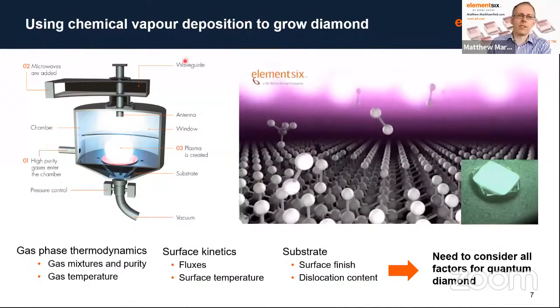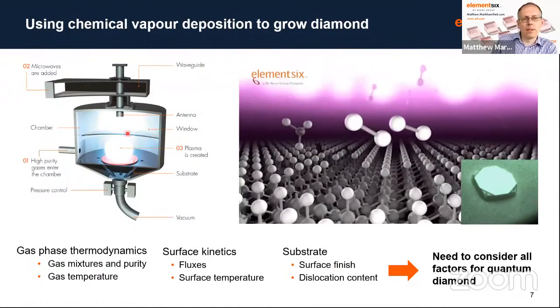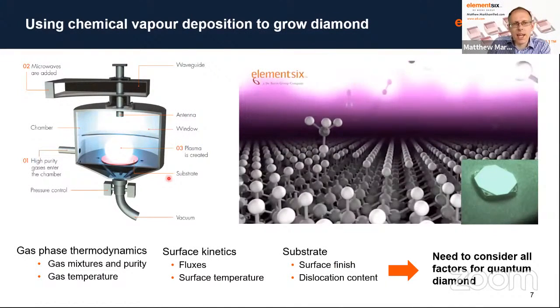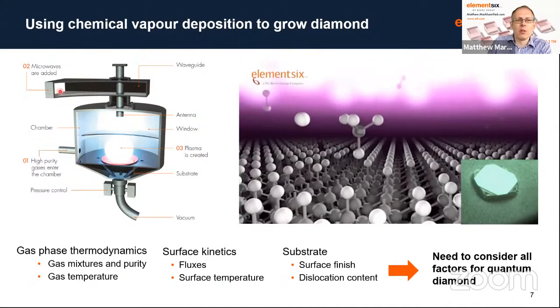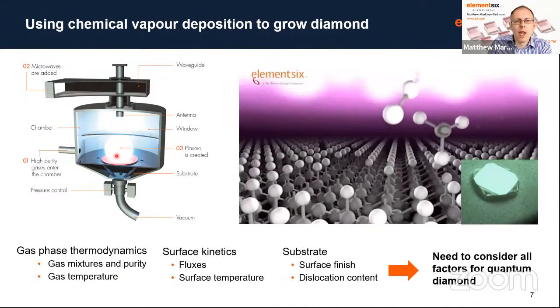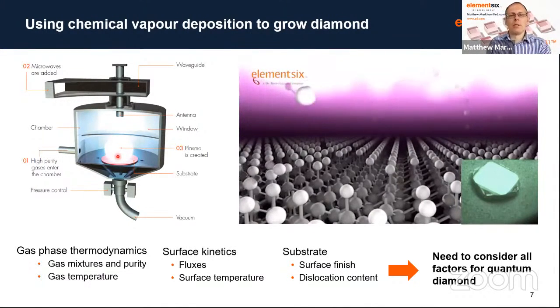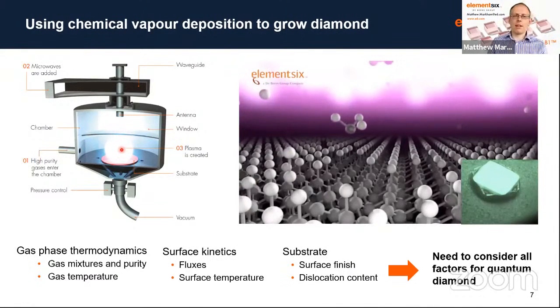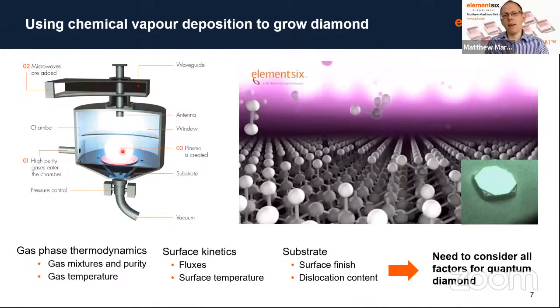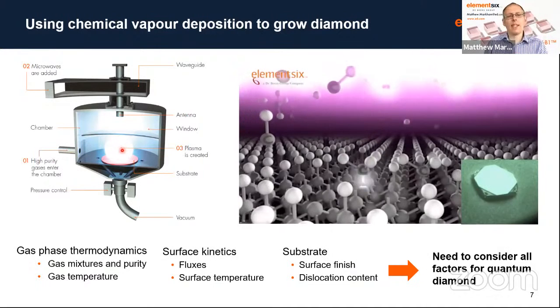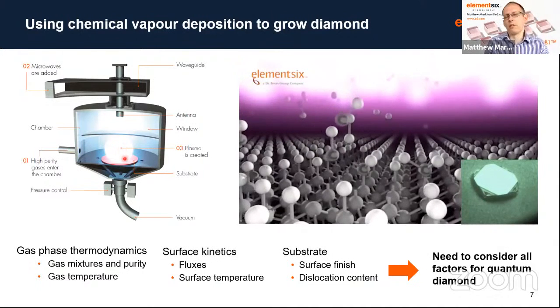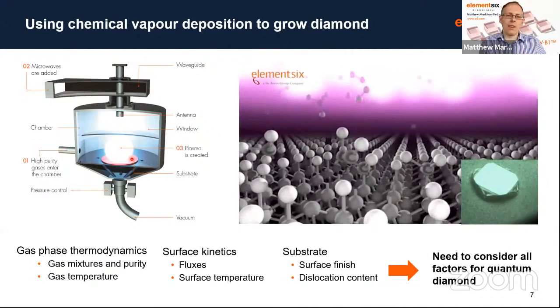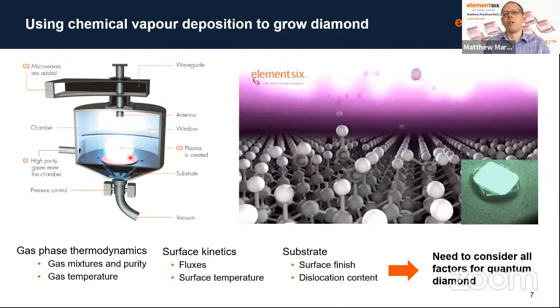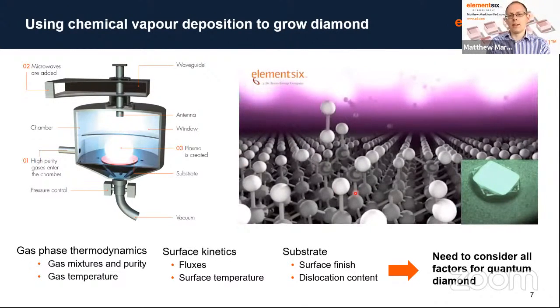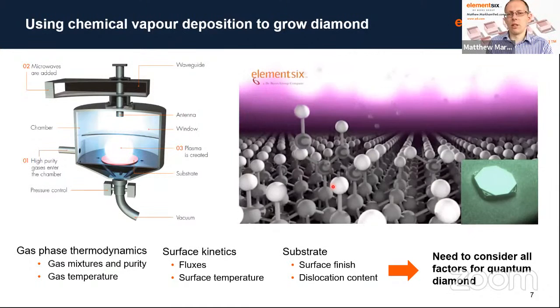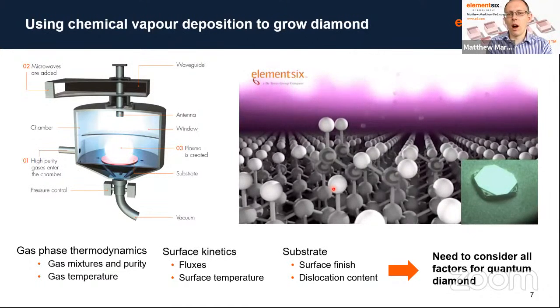And so in our reactor, we use a microwave assisted process, which is basically a microwave chamber into which we inject microwaves. The gases we put into that chamber are things like hydrogen and a carbon-containing gas such as methane. Those are obviously the two key ingredients, and then you add things like dopants in there, such as nitrogen, to add into the material. This cartoon here just basically shows the process and the role that hydrogen plays.